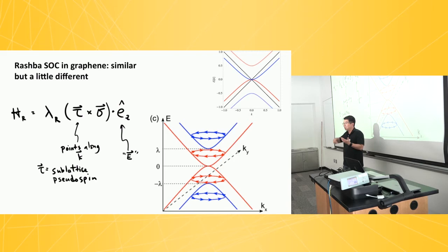So when people started looking at this kind of induced spin orbit coupling, first people said, let's do weak localization, because weak localization has some models and it'll flip over if there's spin orbit coupling. So there have been various ways, but they're kind of indirect. And just within the last year, people have been able to measure, for example, the lifetime of spin that's out of plane versus the lifetime of spin in plane. If you don't have spin orbit coupling, they're all going to be pretty similar. But if you can create a big spin orbit coupling that has a certain preferred axis, then the out of plane and in plane will be quite different. Those experiments first came out in the last half year or so.